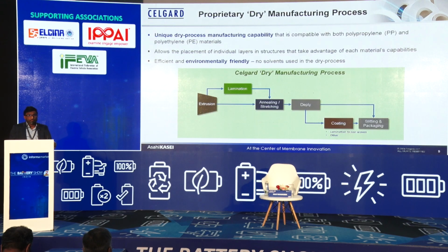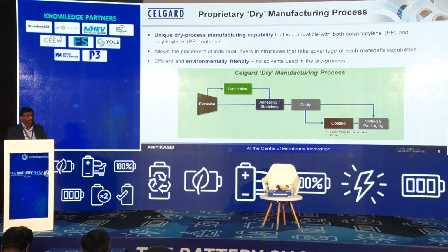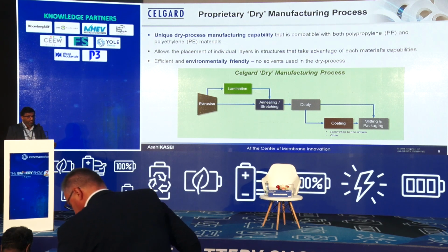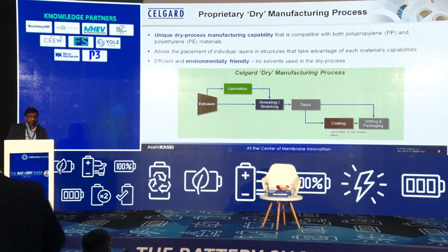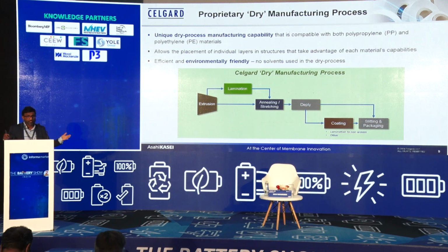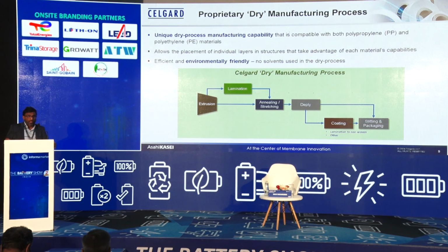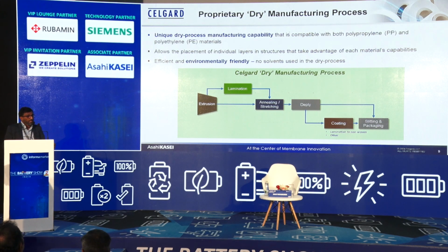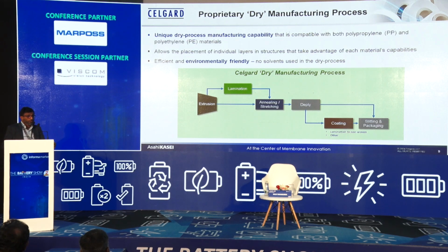So this is a process flow diagram for dry manufacturing. Wet manufacturing is very, very complicated. It has to be a very long line, and it needs heavy investments. But dry manufacturing is very compact. It starts from extrusion of the polypropylene material, which is what we use for the dry separators. After that, we have a very critical process called annealing and stretching.